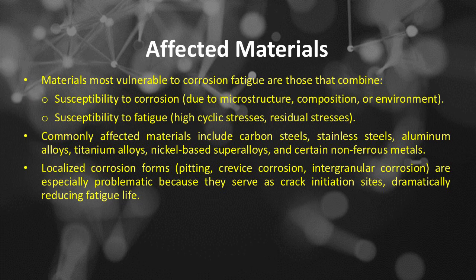Materials most vulnerable to corrosion fatigue are those that combine susceptibility to corrosion, due to microstructure, composition, or environment, with susceptibility to fatigue, such as high cyclic stresses and residual stresses. Commonly affected materials include carbon steels, stainless steels, aluminum alloys, titanium alloys, nickel-based superalloys, and certain non-ferrous metals. Localized corrosion forms, pitting, crevice corrosion, and intergranular corrosion, are especially problematic because they serve as crack initiation sites, dramatically reducing fatigue life.